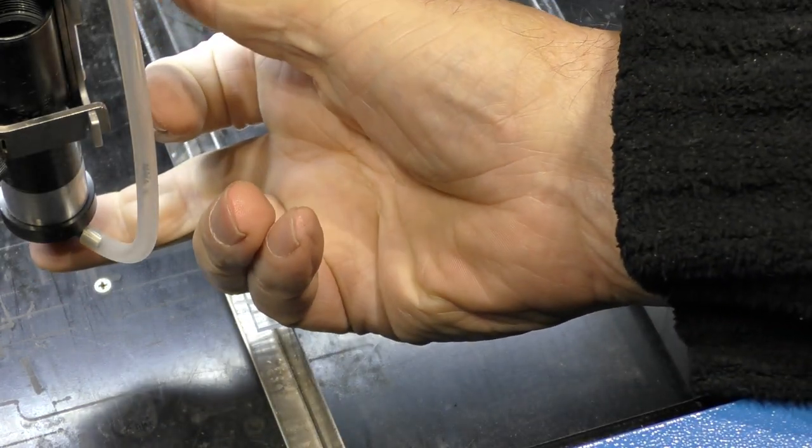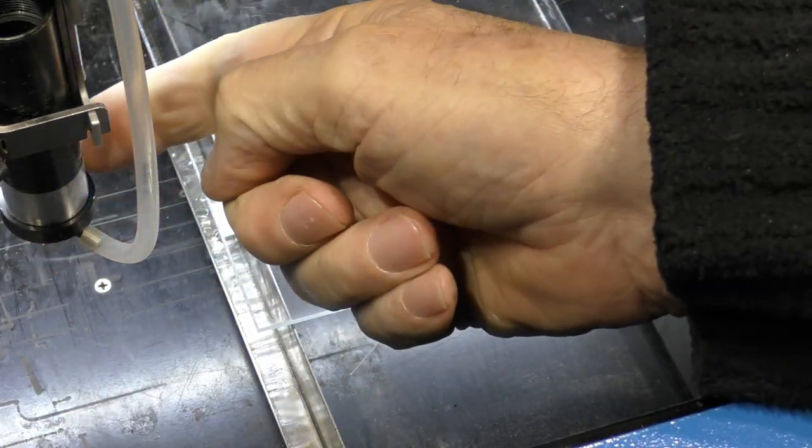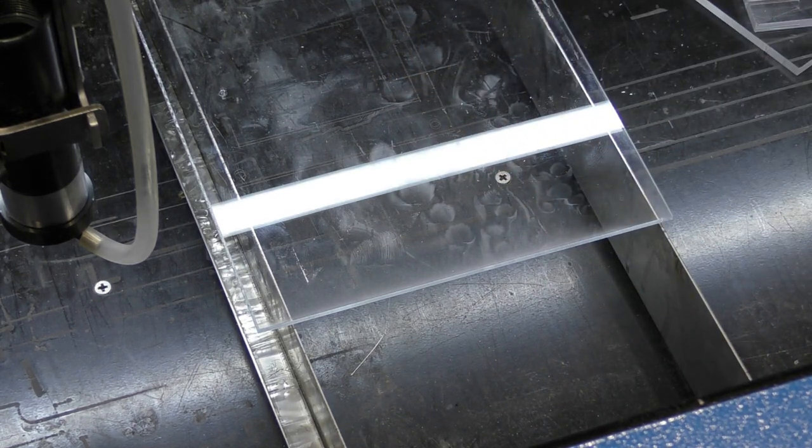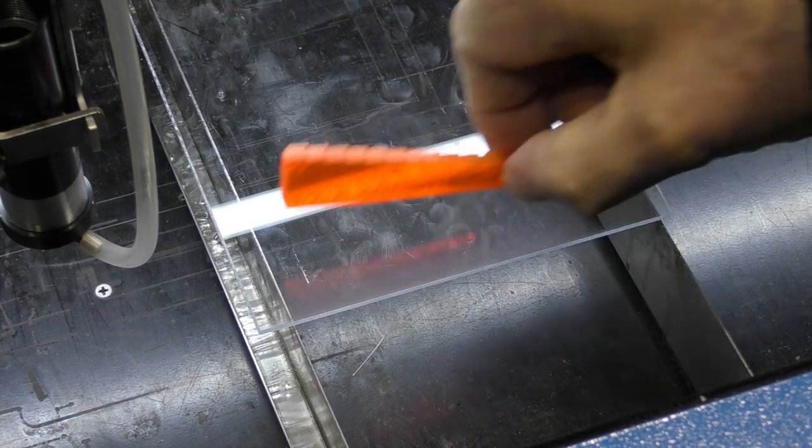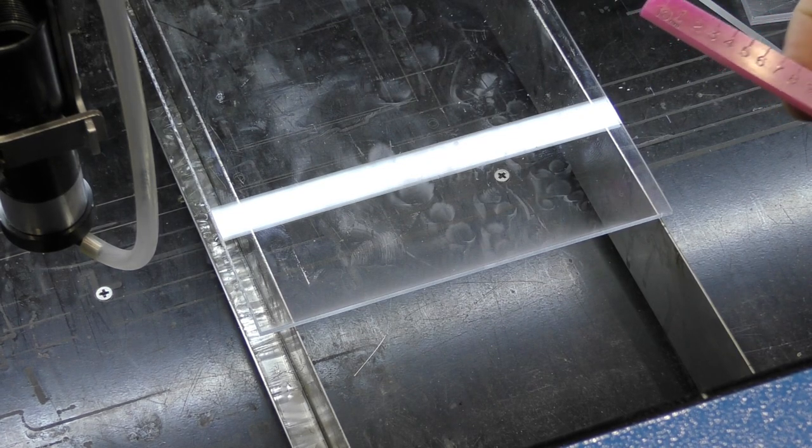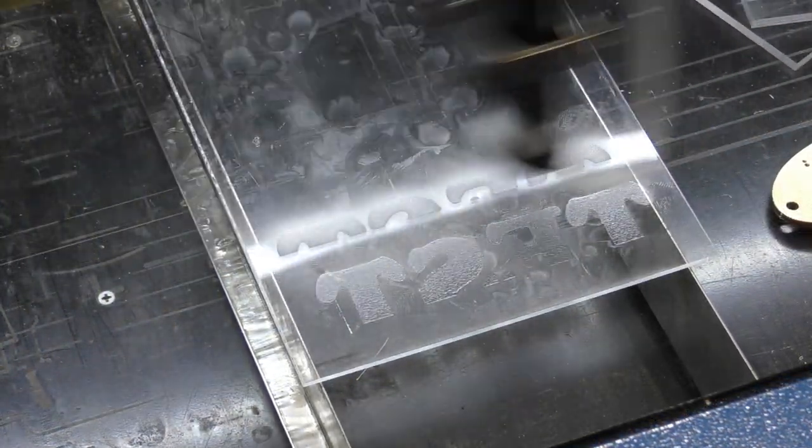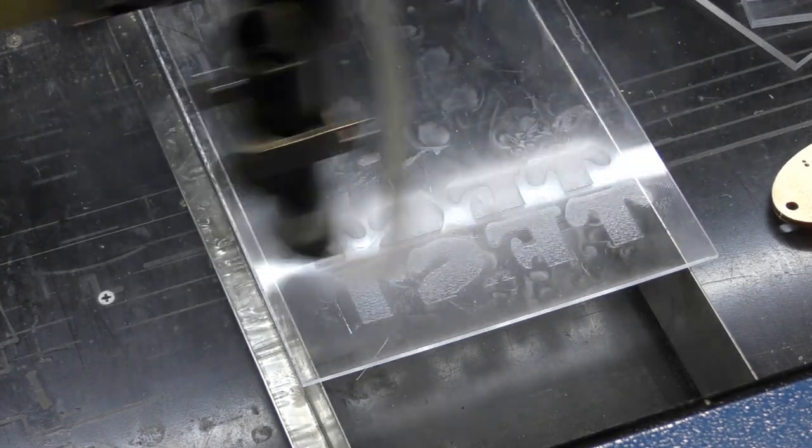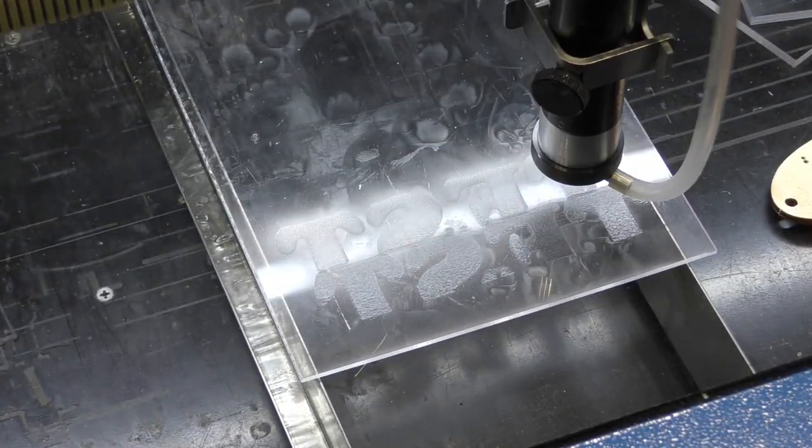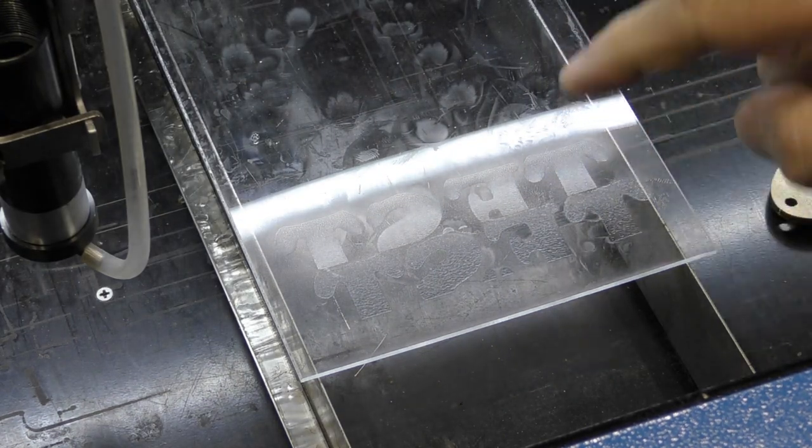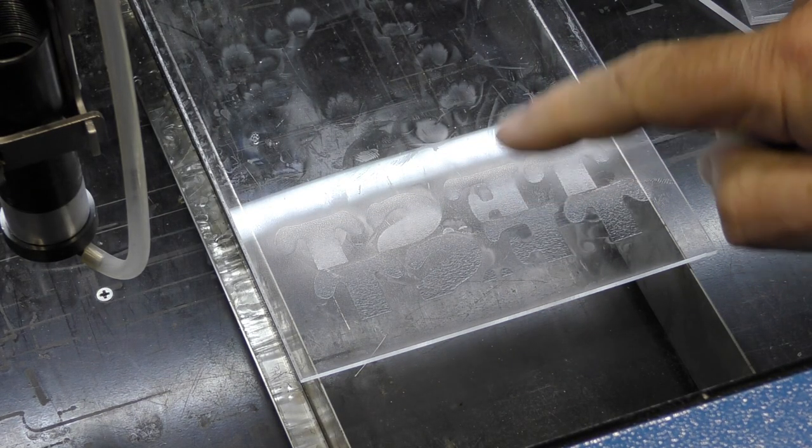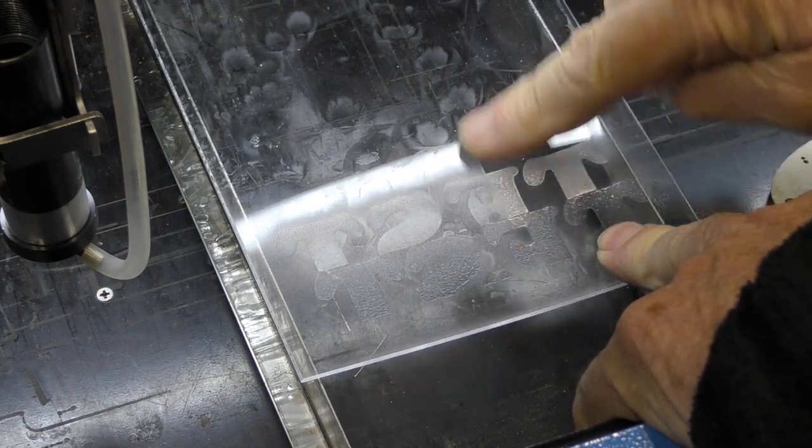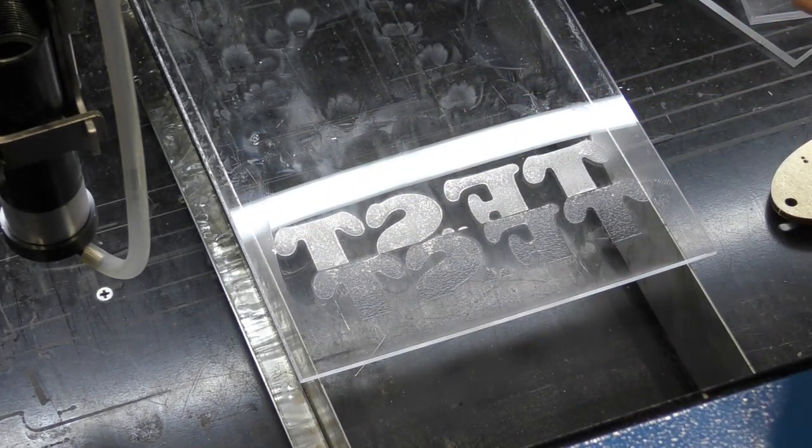So I've changed away from the one and a half inch meniscus lens that I had in here and I've now got the compound engraving set in there which gives me about a 21 millimeter focus. And instead of 15 millimeter air gap I've now got down to about 11 millimeters. I can see we're doing a lot of damage. I can hear we're doing a lot of damage. But what we've got to remember now is this white that's on here is not necessarily the white that we're looking for. This is crap. Look. But you'll notice it's not sticking to the job. It's just dust.